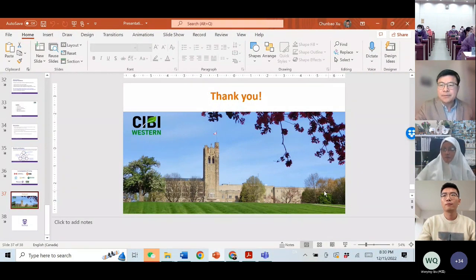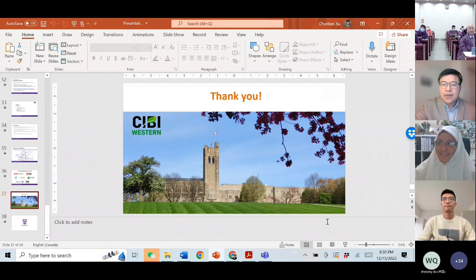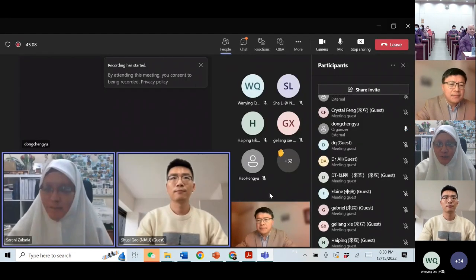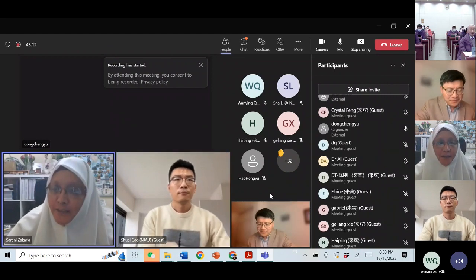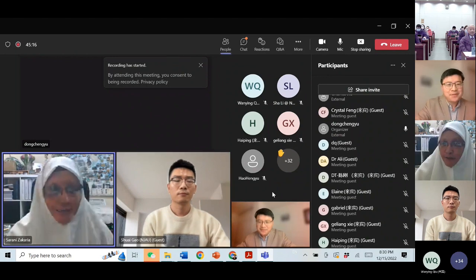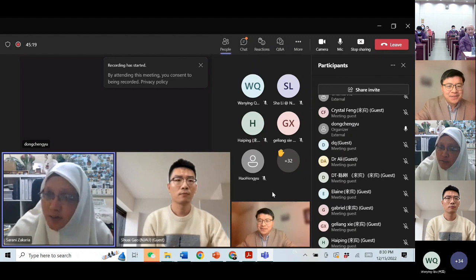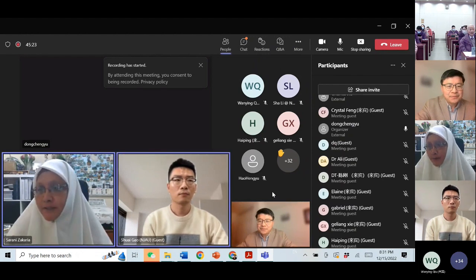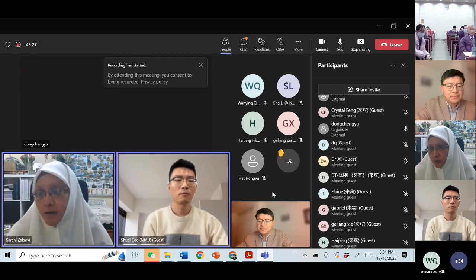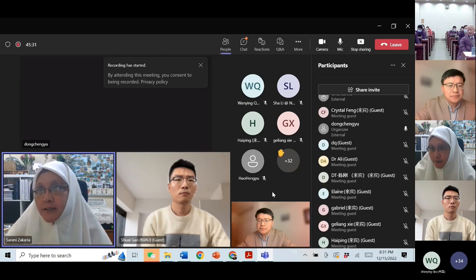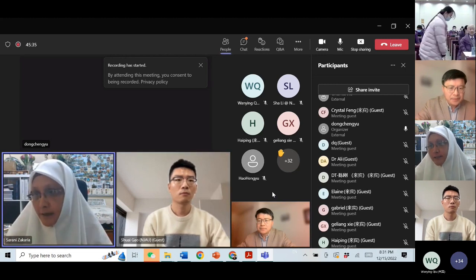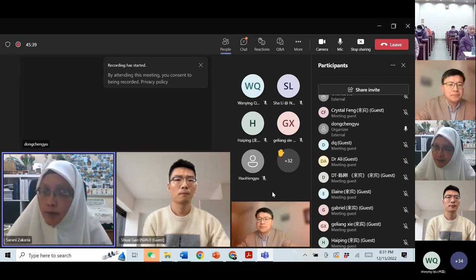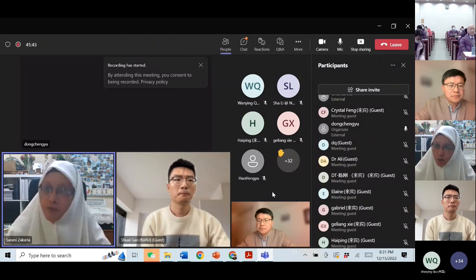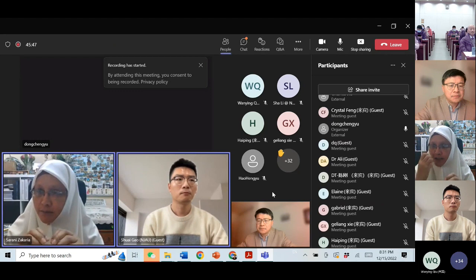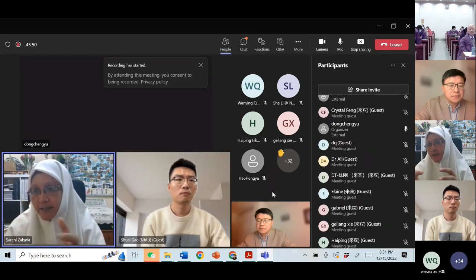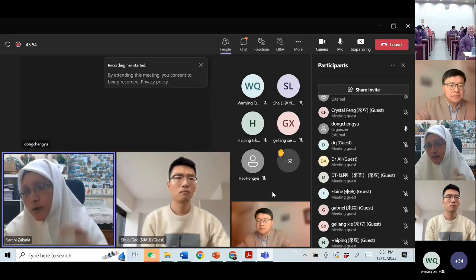Professor Xu. Okay, please. So any questions? Okay, Professor Zhu, I'm Sarani again from UKM. Great honor to meet you. I graduated from Canada also. I just want to ask you, we know that lignin is very unstable, tends to polymerize and so on. When you try to extract lignin from the wood, we know that 100% of lignin is contained in the middle lamella and a high proportion in the secondary wall. But when you extract the lignin intensively from the wood, how do you make sure that the cell wall structure does not collapse, because it is glued by the middle lamella from one cell wall to another? That is my first question.